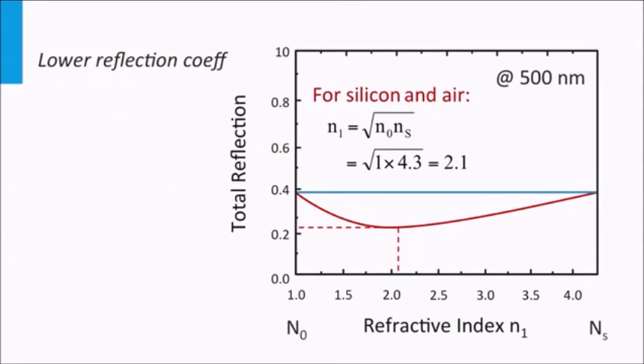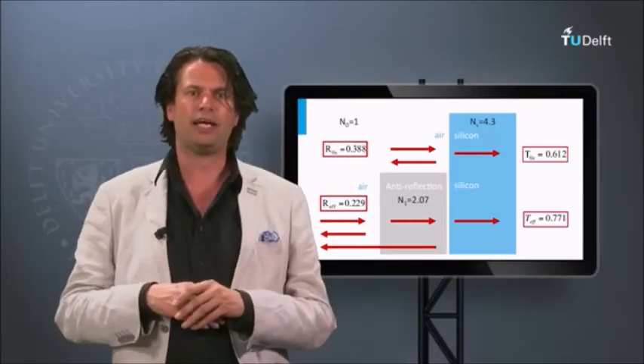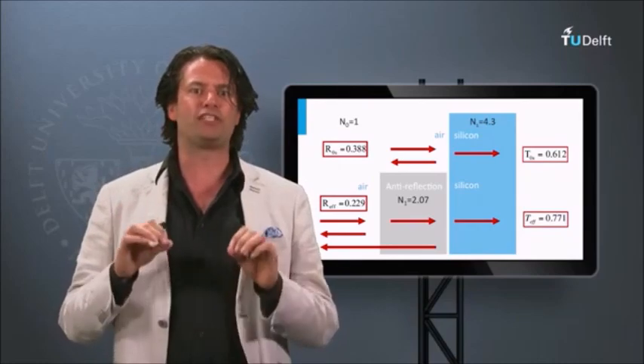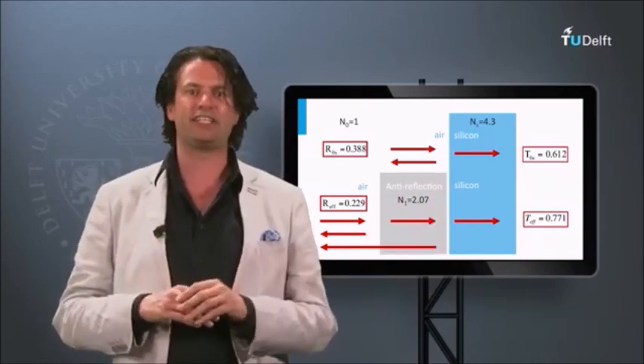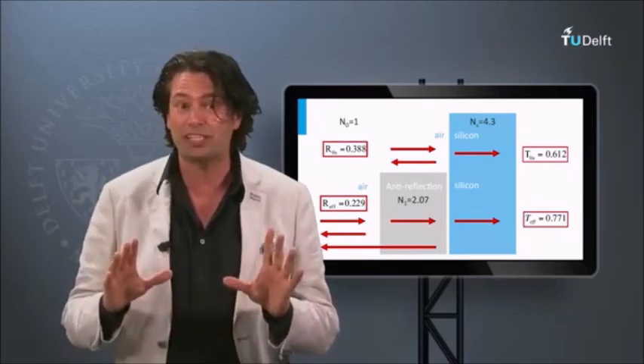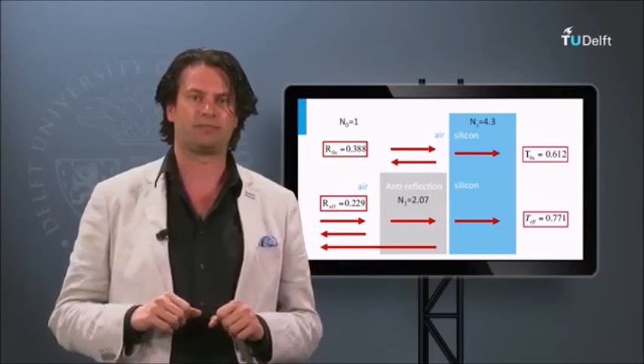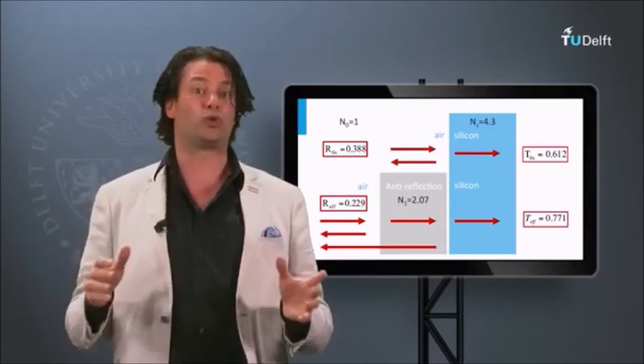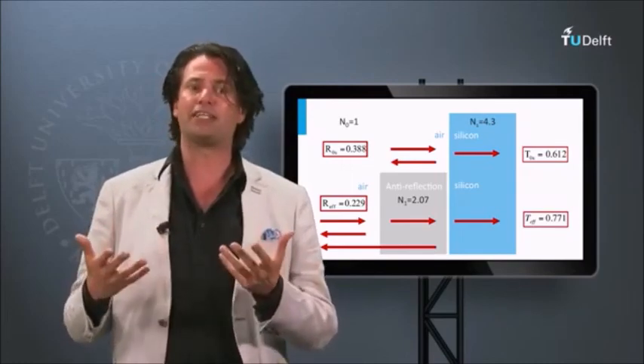We then plot the reflection coefficient of this example versus the refractive index of the interlayer. The blue line is the reference reflection without interlayer. The red line is the reflection with interlayer. The red curve has a minimum. This minimum is exactly at the value equal to the square root of the product of refractive index N0 and Ns. In this example, by inclusion of a single interlayer, the reflection at the interface can be reduced from 38.8% down to 22.9%. Using more than one interlayer, also called refractive index grading, this reflection can be further reduced.